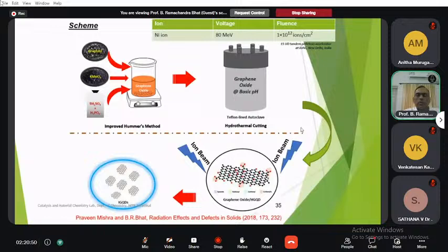These graphene quantum dots can also be obtained by ion beam irradiation. You get graphene oxide here, and on ion beam irradiation, you can cut it into smaller pieces, and thus the ion beam irradiated graphene quantum dots are obtained, and this we have reported in Radiation Effects and Defects in Solids.